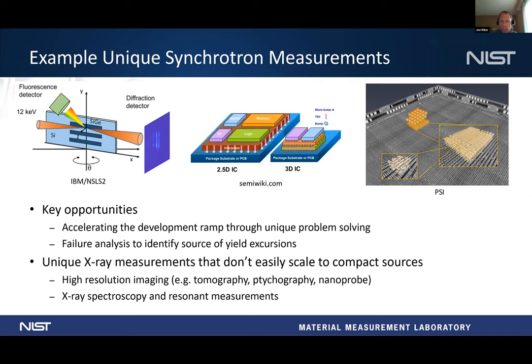But you can imagine with lab systems, you can't quite get the resolution that you need, because as they get smaller and smaller, you suddenly might have a 200 to 500 nanometer thick structure on the copper pillars that are connecting the different structures. And to be able to actually resolve anything of that, you're going to need 50 to 100 nanometer resolution at least. And so you can't really do that over a very large area with small lab-based X-ray systems. And then on the right is the Paul Scherrer Institute work where they've done 3D ptychography looking at chips, where you can then zoom in and get down to about 10 or 11 nanometer resolution on the chips.